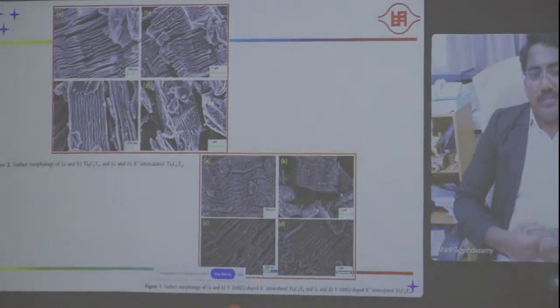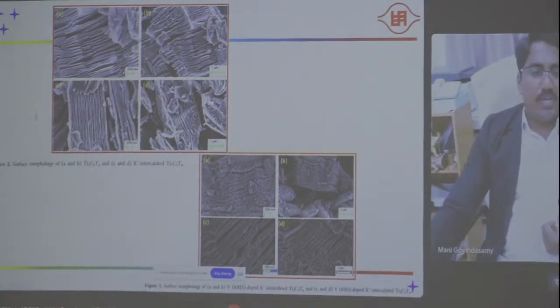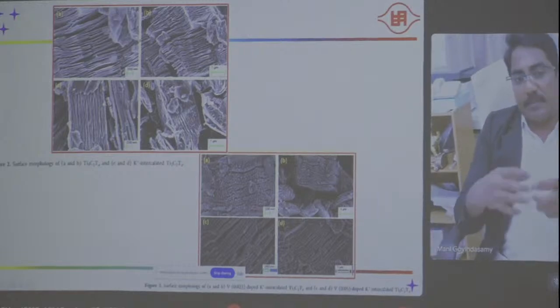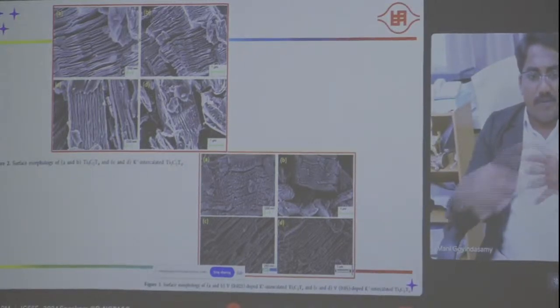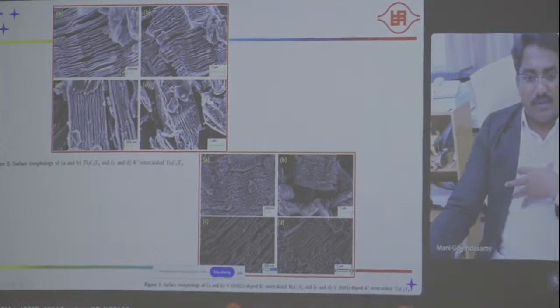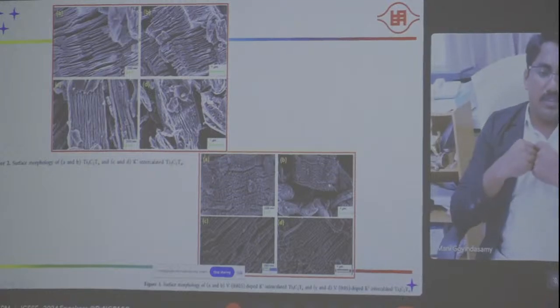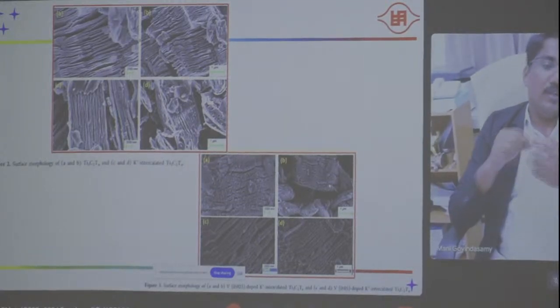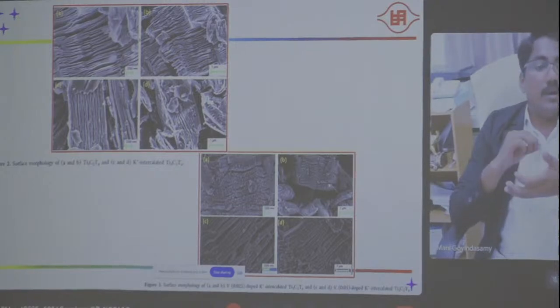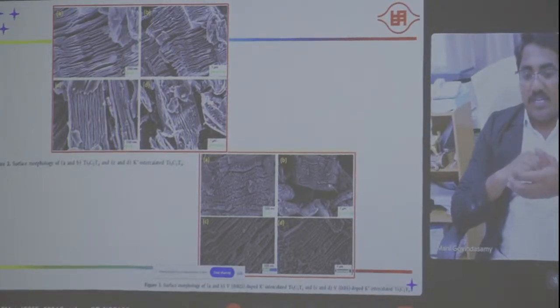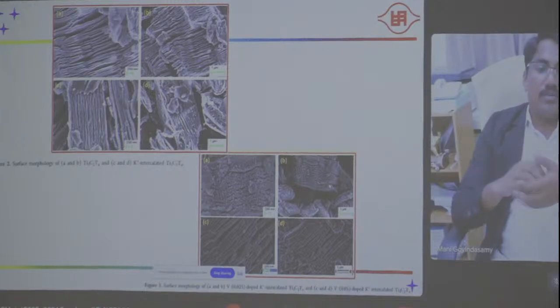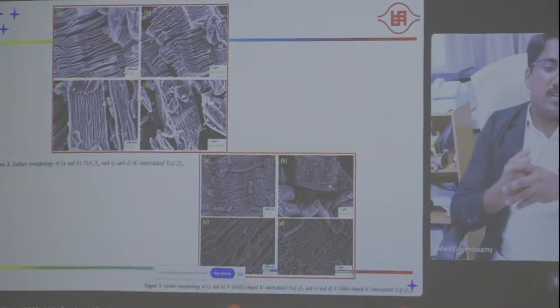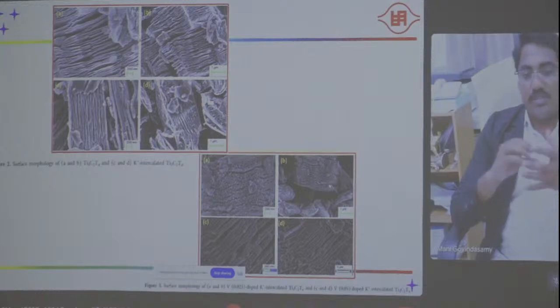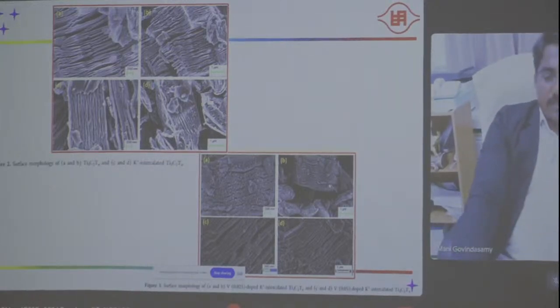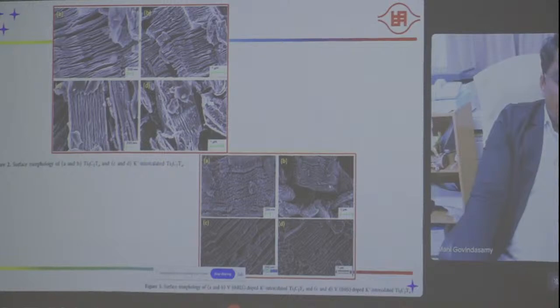So going from the MAX phase to MXene, see the interface, the layers will be separated. After the doping, we got different vanadium doping at different percentages. When we dope the MXene with vanadium, we can get a higher energy density. Power density depends on the carbon related materials, right? When we go for metal or metal oxides, we can enhance the energy density. So in this work, we developed energy density using MXene related materials and vanadium doping.